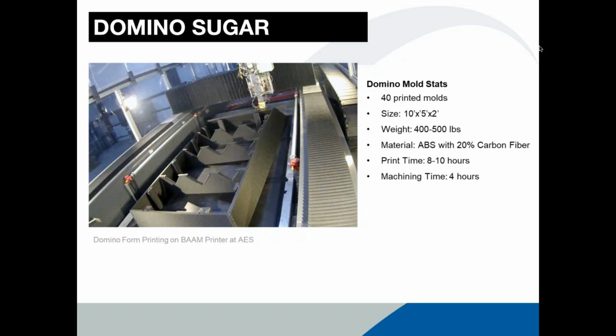So to give you a little bit of numbers here, print time was anywhere from 8 to 10 hours, depending on the form that we were printing. And then machining took about an additional 4 hours. So in about one shift, we could print one of these forms, and in about half a day, we could machine it and it would be complete.